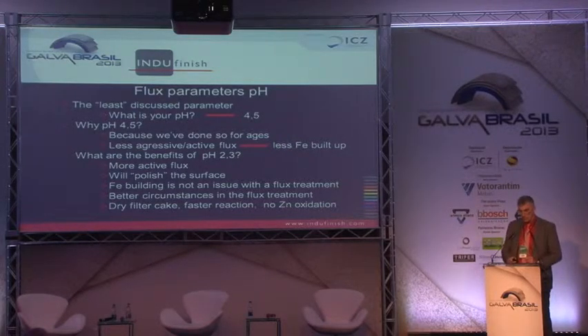Why are we using 2.3? First, we're polishing the surface, and next to that you will get a much drier filter cake. And this filter cake you have to get rid of. If the level of fluid in the filter cake is high, you have to dispose of more material. We've got a filter cake with a dry content of about 40–50%. Very dry, less money for disposal.